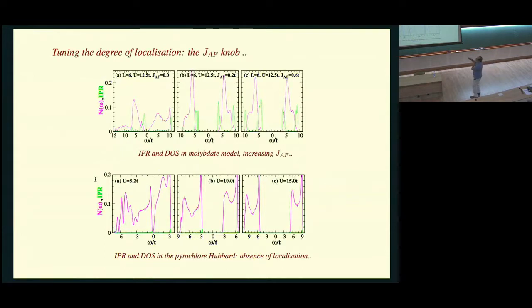If I increase JAF, this is to sort of put some of the blame on the JAF, I go to successively larger values of IPR. I can only do 6, and I can do 4, 6, 8, let us say. We tried 6 and 8, okay, but beyond that I cannot anneal the system. In fact, I can do 0 temperature calculations on larger sizes. I cannot do the finite temperature. So if I did just Hartree-Fock, I can probably do much larger sizes. But it turns out between 6 and 8, this trend is consistent. That the localization length is so short that the boundaries of the system don't seem to matter anymore.